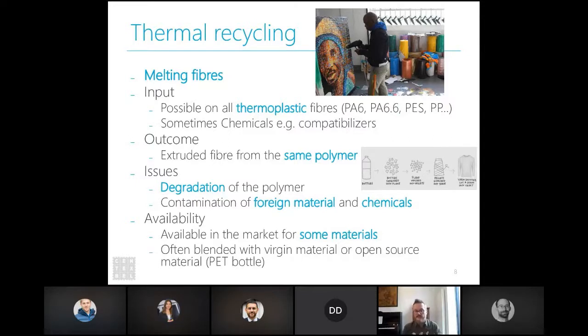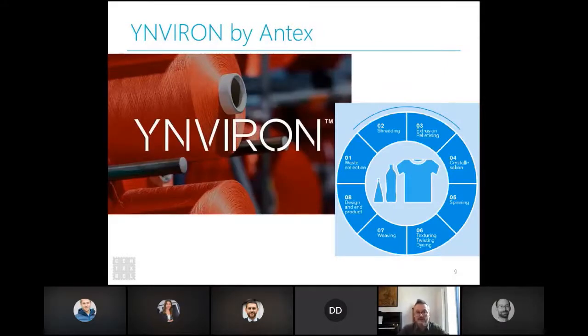There is a degradation of the polymer. This degradation you don't have for the mechanical, where you have mechanical damage done to your fiber. Contamination of foreign materials and chemicals is an issue because they remain inside the polymer in a lot of cases. This is in the market for some materials, but often, like for mechanical recycling, virgin material or open source material is included into the fiber to maintain a certain quality level. An example of a fiber is the Ynviron fiber from Antex.